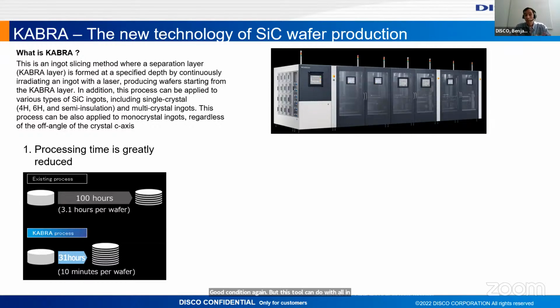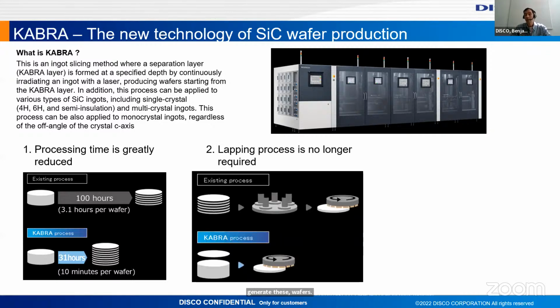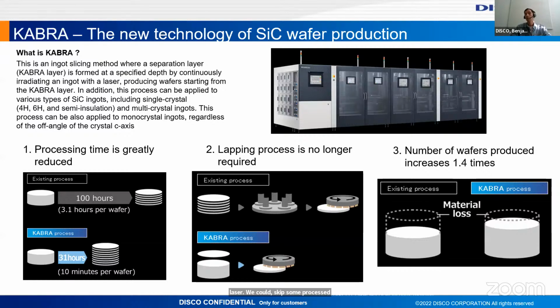And compared to the classical wire saw, we could reduce significantly the process time to generate these wafers. Also, due to the precise and gentle interaction of the laser, we could skip some process steps, so you don't need to do so much preconditioning after the splitting. And finally, which really is directly money in the pocket of our customers, we can reduce the kerf loss. That means the material that is wasted when you cut silicon carbide from the ingot. So that is our approach for the silicon carbide wafer production, and we call that KABRA.